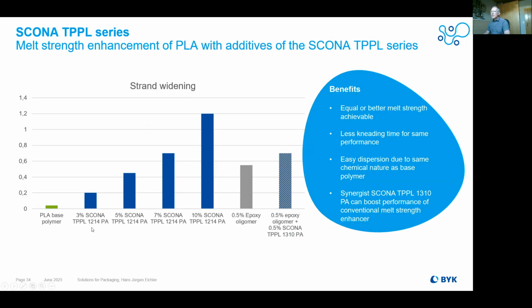And what you see here is with different amount of our TPPL 1214, you are really getting nice improvement in the strand widening, which means we have really nice increasing in the melt strengths. Here you see some materials which are in the market. So epoxy oligomers are quite often used. And what we did is we used these epoxy oligomers in concentration of 0.5 alone. And beside that, we worked with our acrylic acid modified material in a combination. And you see also here with the traditional epoxy oligomers, we see some improvements, but the values which you can reach with our 1214 material are on a quite higher value.